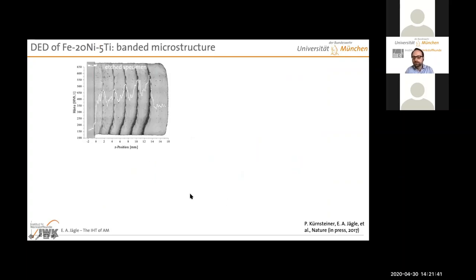Okay, and now having said all that, this is becoming more and more complex. We went to iron 20 nickel 5 titanium. Why? Well, because we put it into the project proposal that we would work with both aluminium and titanium, and we thought it would probably be a similar result to the aluminium. It's what can come out of this that is interesting. It turns out something quite interesting comes out of this. I call this the zebra specimen for obvious reasons. If you look at the etched specimen, of course, in the paper, we don't call it zebra specimen. We call it Damascene steel deposited by additive manufacturing.